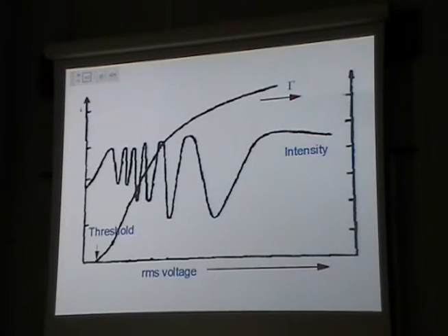As I put it between crossed polarizers, I go from a quarter wave plate to a half wave plate to a zero wave plate to a quarter wave plate to a half wave plate. Every time I go through one of those transitions, I go from light to dark. So I go bright, dark, bright, dark, bright, dark, bright, dark as I increase. So each one of these blips represents a 2 pi variation of this retardance.